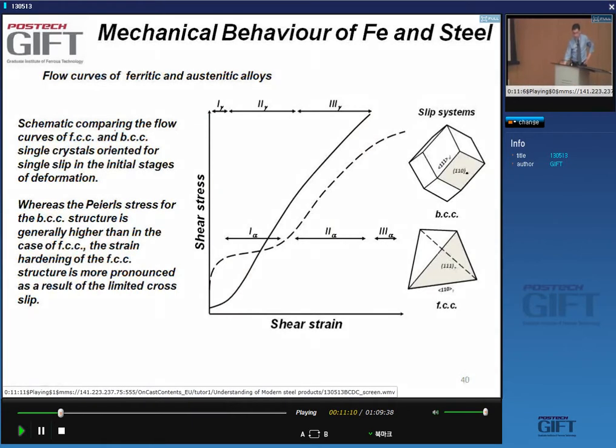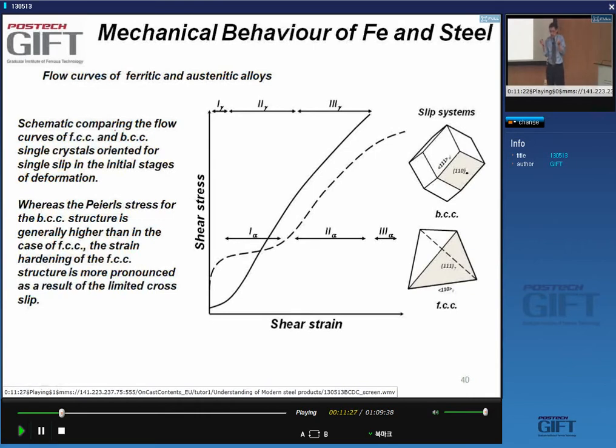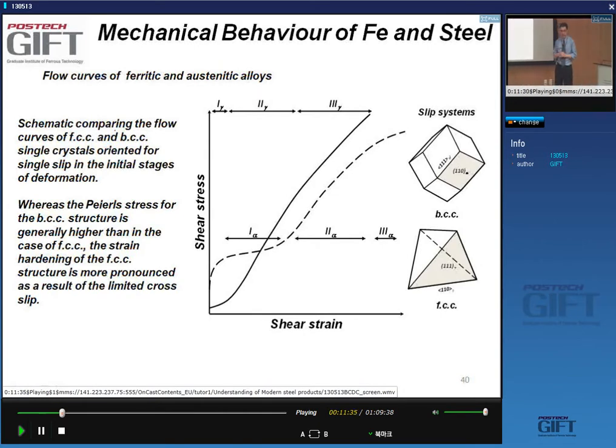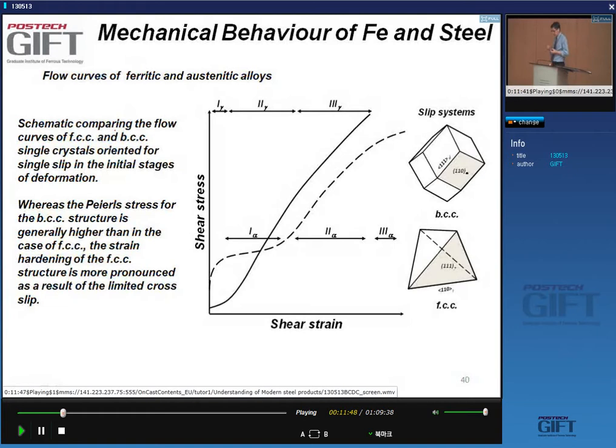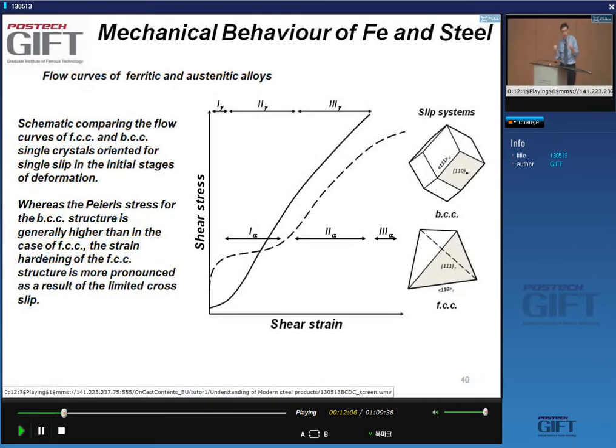Can we see the effect of cross-slip or absence of cross-slip when testing alpha iron and gamma iron, or ferritic and austenitic steel in very pure form? Yes, we can, if we compare the shear stress-shear strain curves of single crystals of alpha iron and gamma iron. The initial yield stress in austenite is lower than in ferrite.